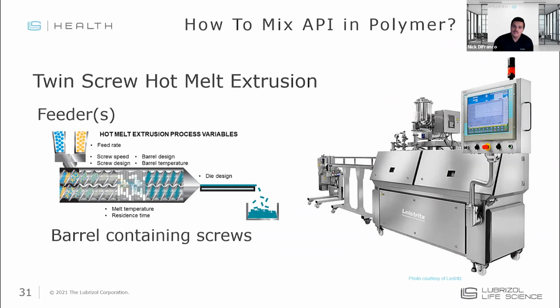There are a few different techniques to do this, but most commonly we use twin screw hot melt extrusion to achieve this. This is a process that uses an extruder with two screws in which the API and the polymer are fed into the barrel of this device, and through the application of heat and shear, they are mixed together to form a homogeneous dispersion. It gives you a compound that is your polymer loaded with your drug, essentially. It's a simplified version of it, but I think it helps get the point across.